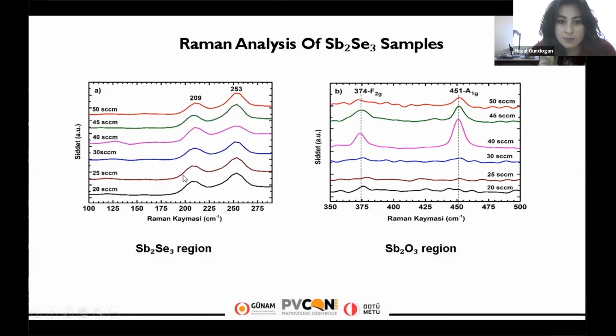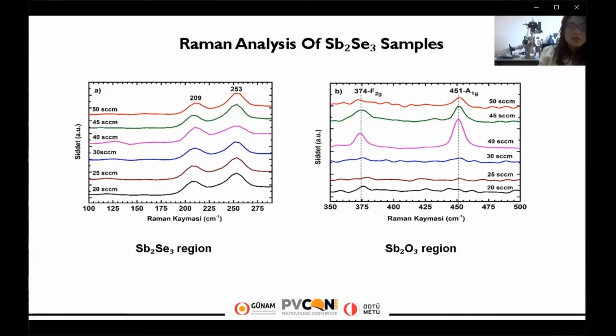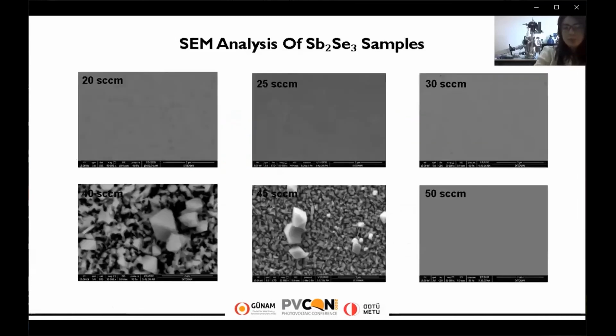If we look at the first graph, all films have characteristic peaks of the antimony selenide structure at 209 and 253. This 209 peak originates from the vibration mode of antimony and selenium, and the other 253 peak originates from the vibration mode of the selenium atom ring.